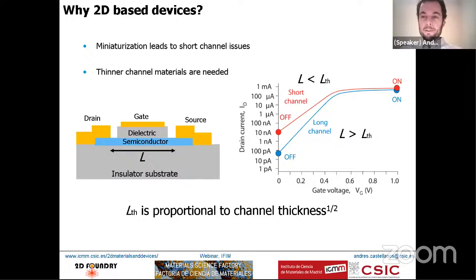Eventually, that is the main goal. But it's technically quite difficult. For instance, in molybdenum disulfide, if you apply 8% tensile strain, you almost close the band gap. So you pass from a semiconductor that has the absorption edge in the visible all the way to the deep infrared. That is the main goal of the project I'm working on, but that is the ambitious goal. The thing is that applying 8% strain in a device is very, very difficult, but eventually it could be done.